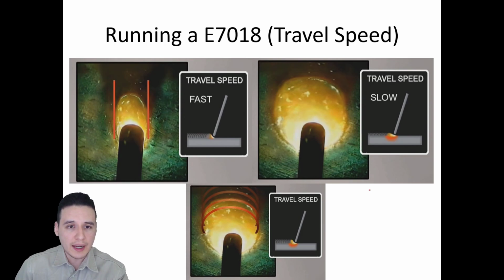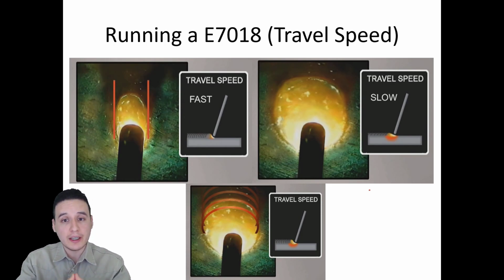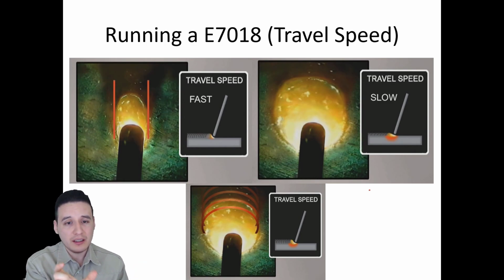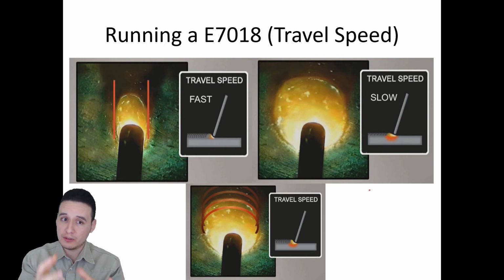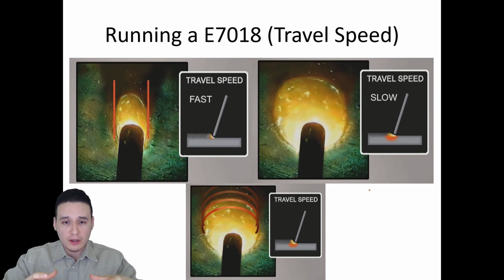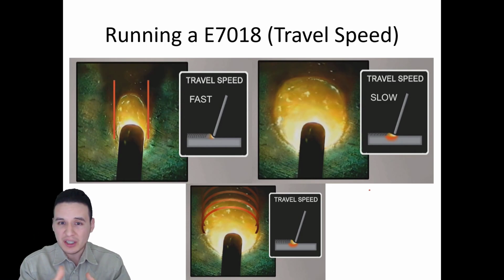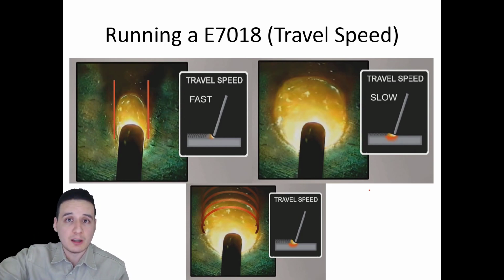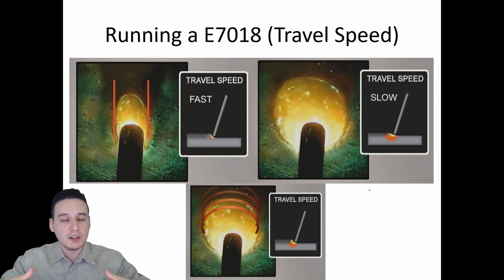So what about travel speed? How do we know if we're going too fast or too slow? Well, if you're going too slow, you're going to notice that your puddle gets bigger and bigger. Even if you're welding at the correct amperage, if you go too slow, you're building up a lot of heat in that area because you're barely moving. So even though you have the right amperage, it's going to feel like you're welding at a much higher amperage because of the heat input. So you don't want to move too slow. Again, if you do, you'll notice your puddle starts to get a little on the big side.